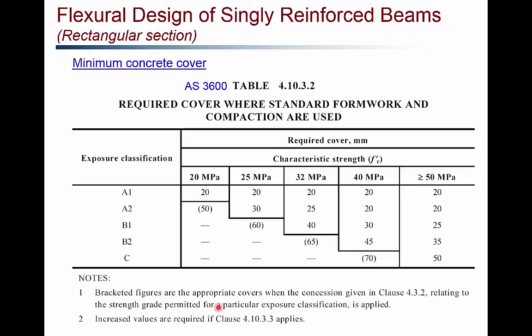Also, we saw earlier that the durability requirement prescribes some minimum effective cover and minimum characteristic strength as well. So AS 3600 Table 4.10.3.2 prescribes the minimum characteristic strength f'c and the cover values for different exposure conditions. For example, for a B1 exposure condition, the minimum concrete strength required is 32 megapascals, and the minimum clear cover required for the beam is 40 millimeters.